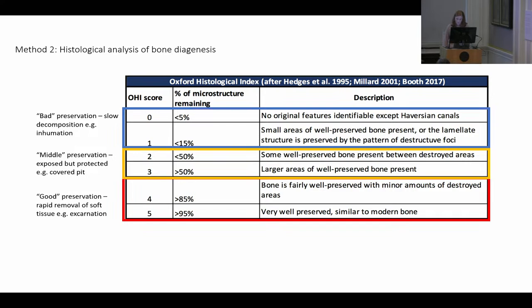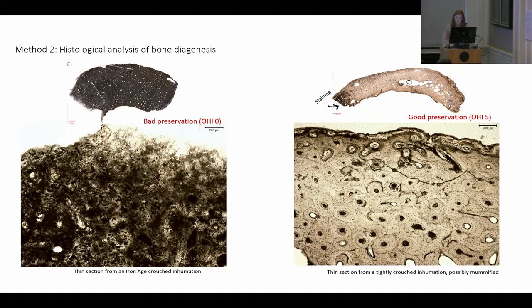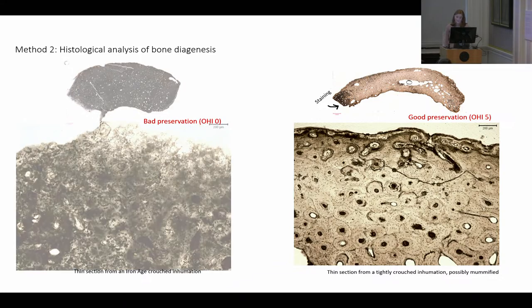And then a score of 4 to 5 means that there's minimal bacterial attack, and this might suggest rapid removal of tissue such as excarnation or mummification. So these two samples here illustrate the difference really clearly. These are from the same site, Hunt's Grove in Gloucestershire. Both of these were probably inhumations in pits. I say probably because the overall preservation of both of them was not very good. But they have vastly different histological preservation.